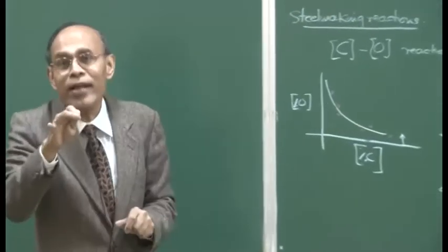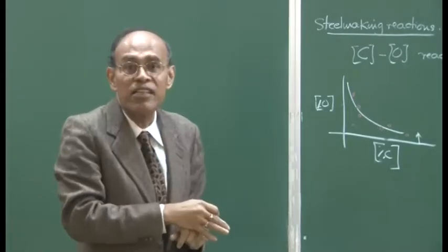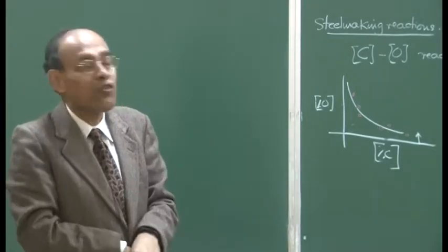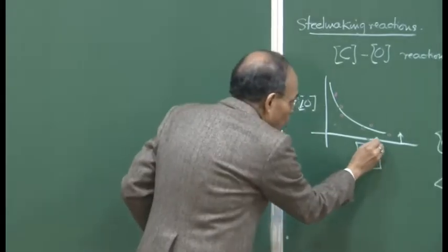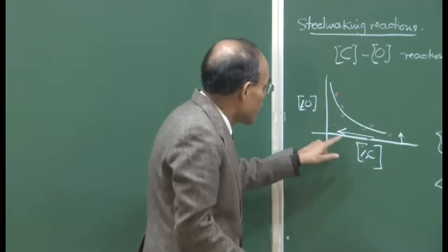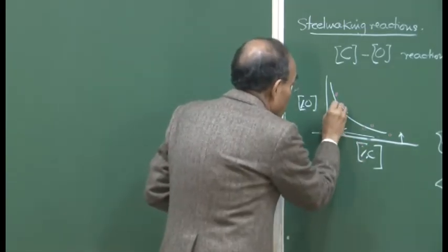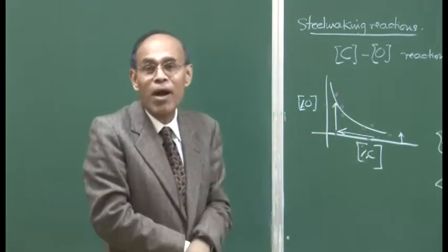It is only when the carbon content has decreased below a certain level that a large amount of FeO starts to form. So as the carbon content moves in this direction during the refining period, you can understand that the carbon concentration is going to be decreasing, and as a result progressively more and more oxygen is going to be present in the bath itself.